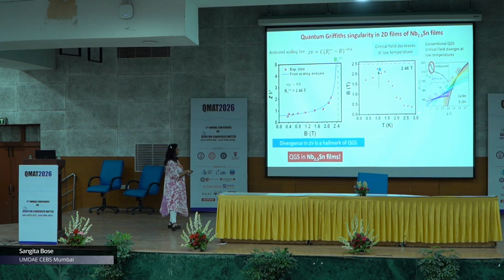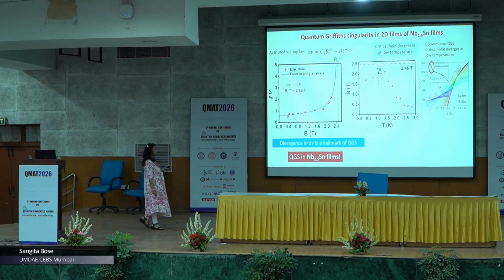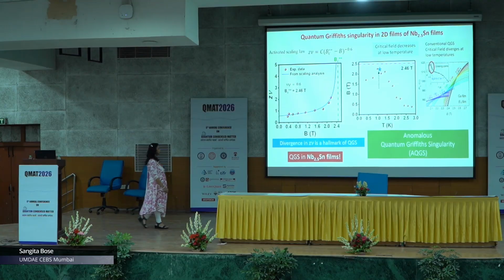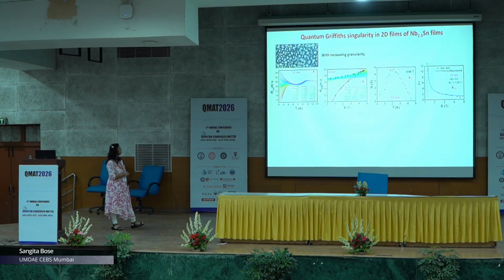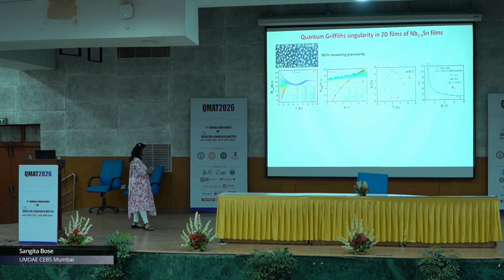So, this is the crossing points. From the crossing points, if you plot the BC versus T diagram, you see that it shows a monotonic decrease or a monotonic flattening. Most of the QGS which has been studied is what people have observed. So, we are basically seeing anomalous quantum Griffiths singularity in our films. So, to corroborate this more, what we did is that we did more experiments.